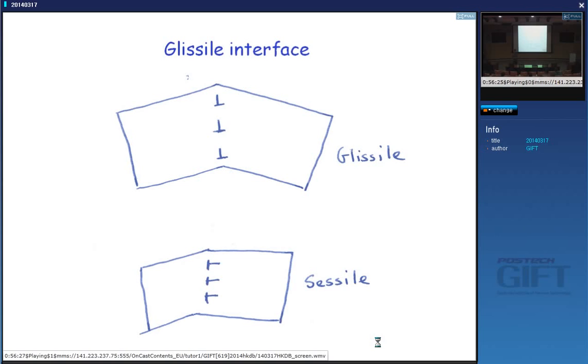Okay, so here we have a single set of dislocations. They're all parallel. And I explained to you that in general, you might have three sets of dislocations. Now, what happens when you have a dislocation like this and another one like this in the interface? They will try to interfere. So if this one cuts this, you will get a step on this dislocation, which is equal to the Burgers vector of this one, and vice versa. So what do we call that step on the dislocation? Or a jog. Jog is the conventional term. Have you heard of a jog? It's a step created on a dislocation when one dislocation cuts through another.